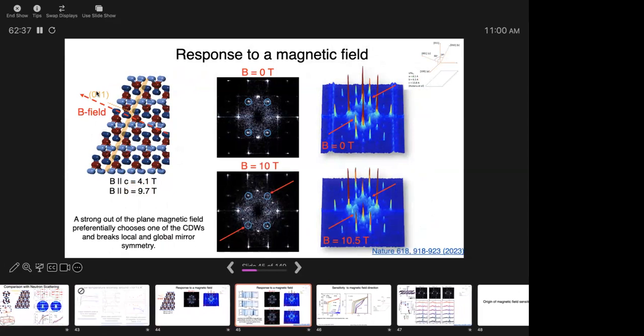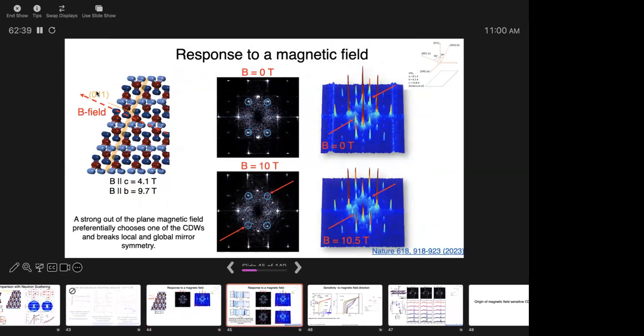In a magnetic field, the first thing is, let me just tell you, this is a perpendicular magnetic field to this plane. In this direction, by the way, HC2 is about 12 Tesla or so. So at 10 Tesla, which is below HC2, what we see is all three peaks get suppressed. So all of the three CDW peaks, 1, 2, 3, are getting highly suppressed with field. This one is almost gone.